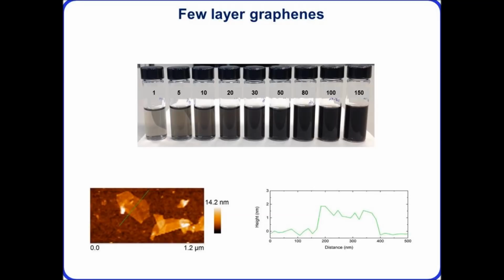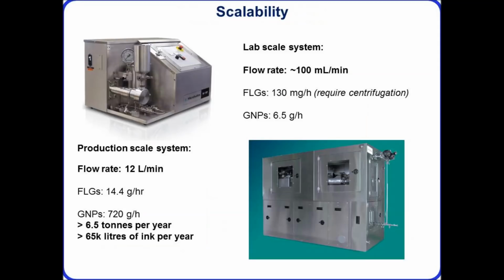Some other numbers in terms of scalability: at the moment we are limited by this centrifugation step, so we have a production rate of around a few hundred milligrams per hour. For the larger scale system, this might increase to around 10 grams per hour. But in terms of usable ink, that's still 65,000 liters of an ink that you can use for inkjet printing or other spray coating deposition techniques. So you don't necessarily need very high concentration to actually produce these transparent conductive films.